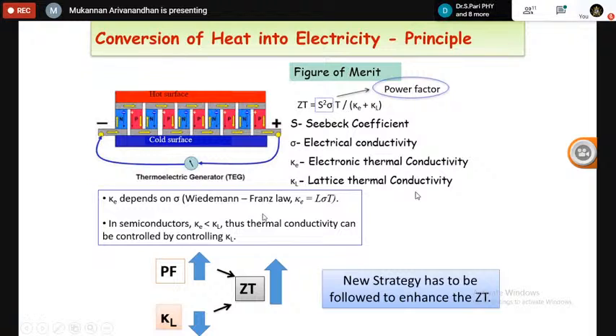But the problem is here. Is it possible to improve the power factor and decrease the thermal conductivity? It's quite difficult, because you can see the thermal conductivity contains two components. One is the electronic part of thermal conductivity, and another one is the lattice part of thermal conductivity. According to the Wiedemann-Franz law, the electronic part of thermal conductivity is directly proportional to the electrical conductivity. So it's quite difficult to independently control the electron transport and thermal conductivity. If you control the electrical conductivity, then thermal conductivity also will be controlled. But if you want to increase electrical conductivity, then thermal conductivity also will be increased.